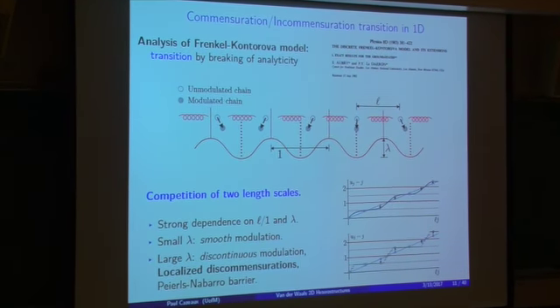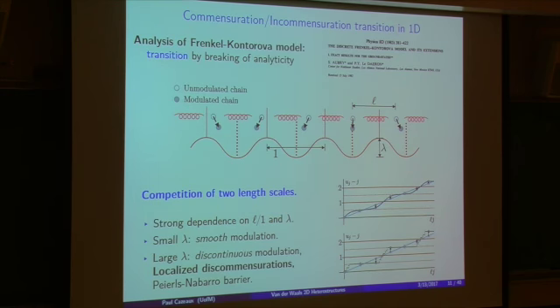But when we introduce this external potential, there will be a competition. These atoms will try to move a little bit towards the nearby wells. But at the same time, they have to minimize their elastic energy. This competition will lead to a strong dependence on both length scales, namely the ratio between the length scale associated with the periodic chain and the lattice constant of this external potential. We can study this and see that we will have a modulation of the chain that can be of two natures. If the external perturbation is small enough, then we will have a smooth perturbation. Basically, the atoms will move a little bit in a smooth manner. That means that if I take this chain and pull from one side, the chain will just follow very nicely.